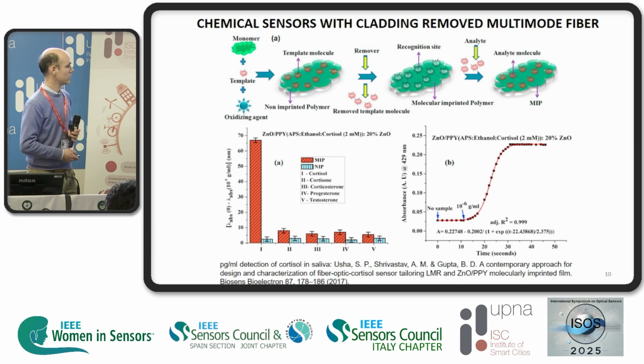And here is one example by the group of Gupta, where he deposited molecular imprinted polymers. Here's a very interesting work, because here in this graph, he compares the performance, this is blue, without molecular imprinted polymer, and the sensor detects cortisol, cortisones, progesterones, many molecules under the same wavelength shift. So it's sensitive to everything, we could say. And with the molecular imprinted polymer, the sensitivity is enhanced a lot, and the selectivity also. So this is the merit for this work. And he reaches in this calibration curve a limit of detection of picogram per milliliter.